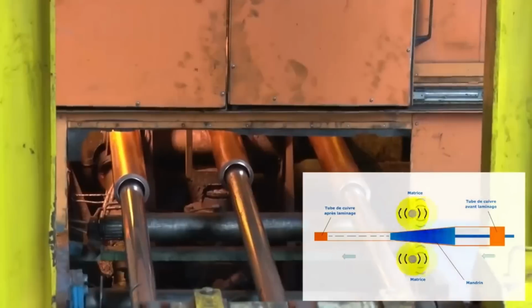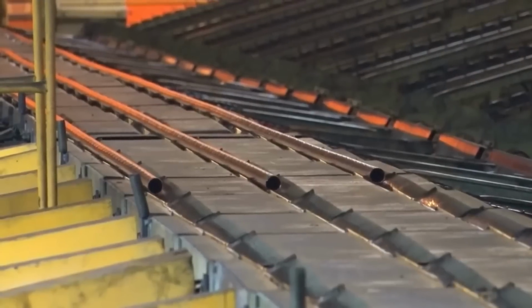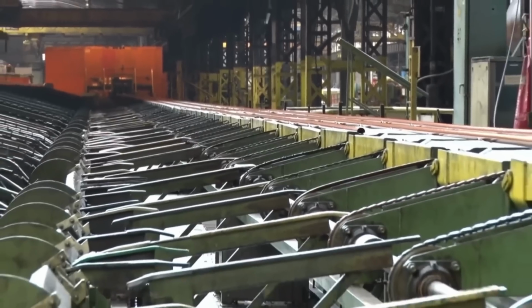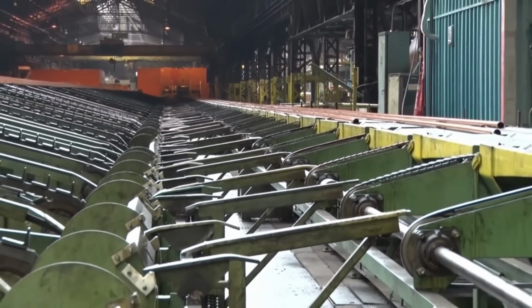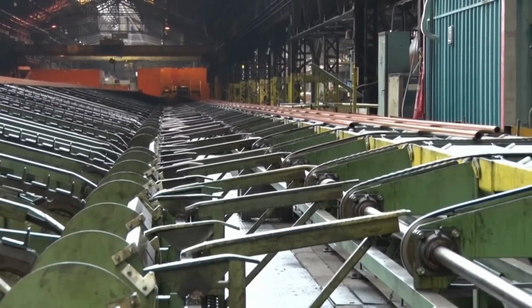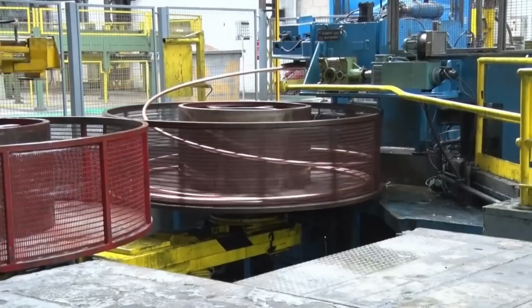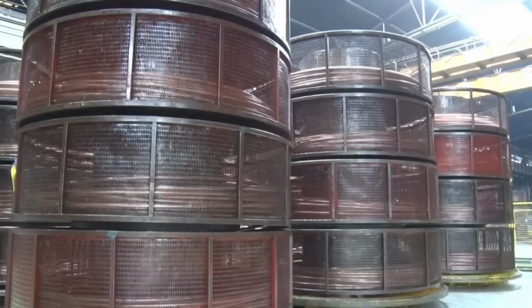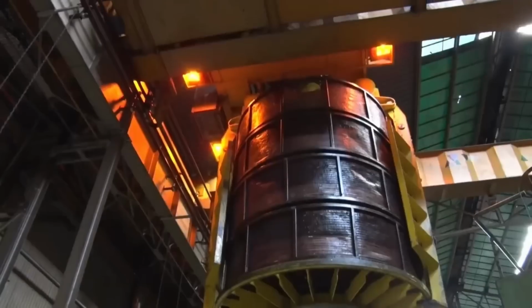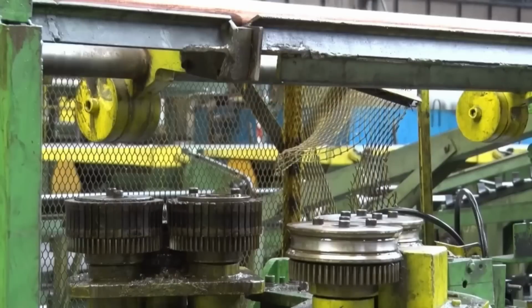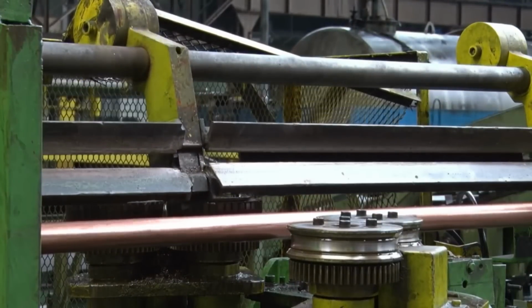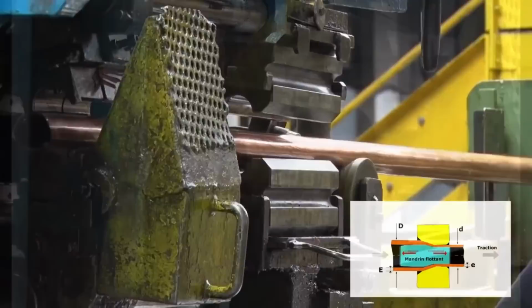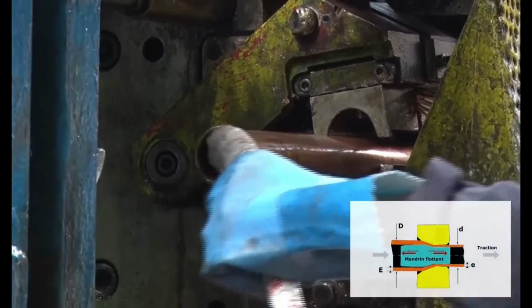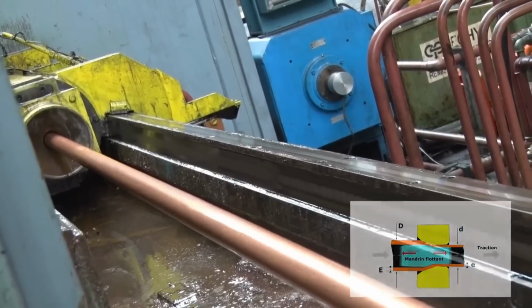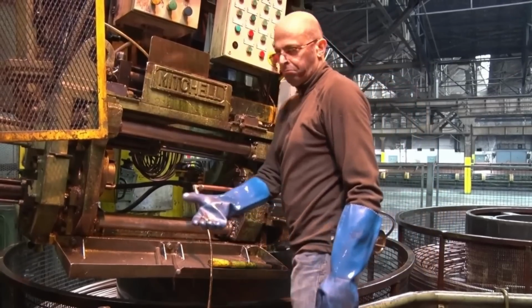Several drawing operations follow, where the tube is drawn between a fixed die and floating mandrels. The dimensions of the mandrels correspond to the outer and inner diameter of the desired tube. The floating mandrel technique allows for working with long lengths at high speeds. Depending on the tube diameter, drawing speeds range from 800 to 1,000 meters per minute. The tube can reach a length of 1,200 meters. For a 14 millimeters diameter tube, it is obtained in a hard or annealed state.